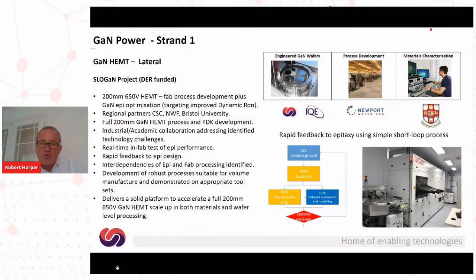Okay, so a little more about the projects that we're working on. So lateral HEMT, so high electron mobility transistors, have been around for quite some time. We're working really at the leading edge of what's available. So we're talking about a 650 volt device being manufactured on 200 millimeter gallium nitride, which again is then being grown on 200 millimeter silicon wafers. So this project's really about the gallium nitride epi material development and also setting up the key processes that we need at Newport Wafer Fab to develop a full 200 millimeter 650 volt GaN silicon process at